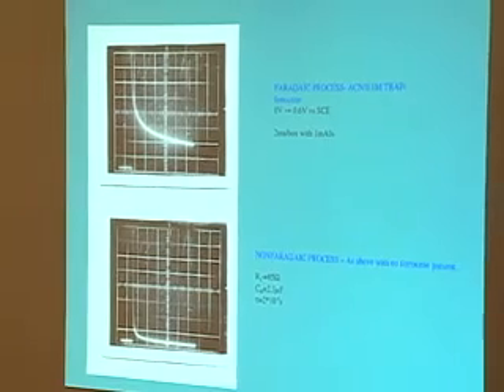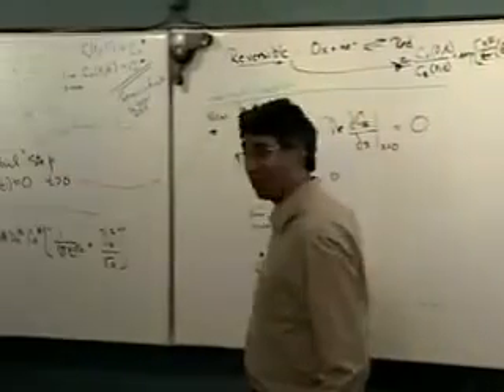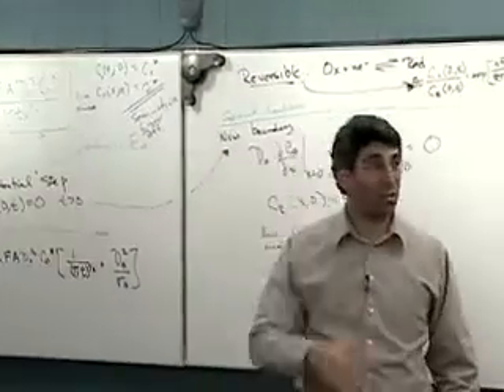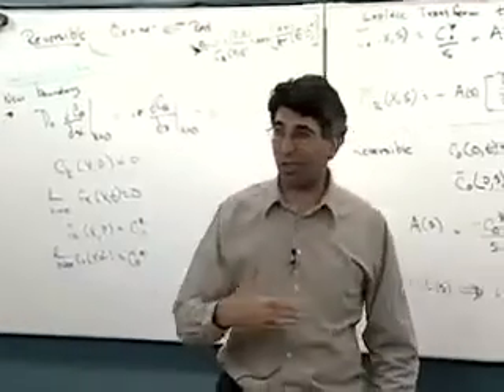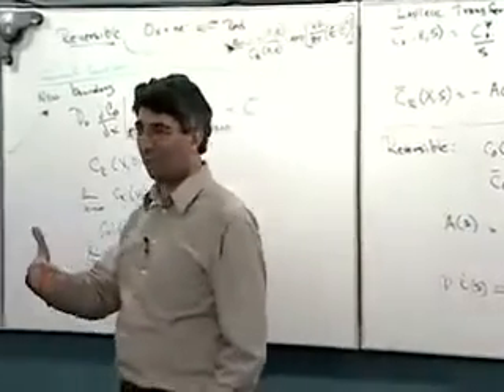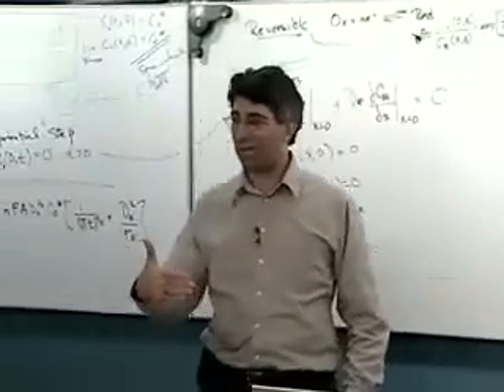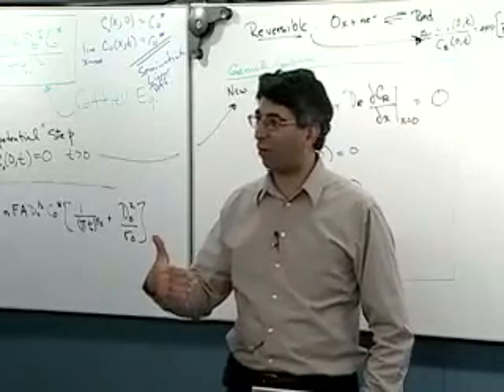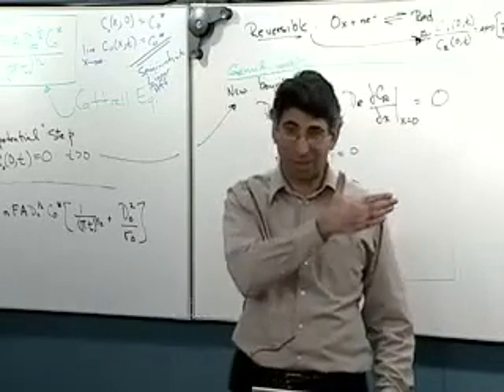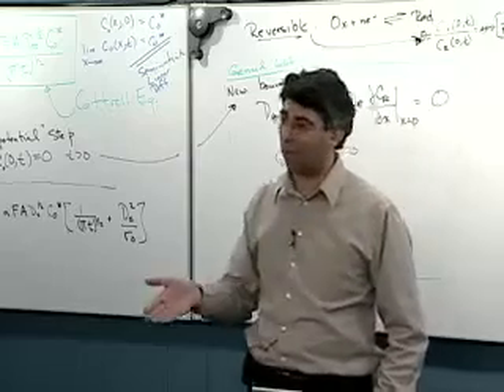Something else that should be pointed out that is not necessarily contained in these equations is the assumption we've made here that we're diffusion limited. There is no other process going on. That is, if some convection sets in, for example, then all the assumptions in here are incorrect. And so we are assuming there's no convection, which means that we have to do our best, first of all, to make sure that the experiment is such that there are no gradients that are set up beyond the concentration gradient that we want. For example, a thermal gradient across the cell.